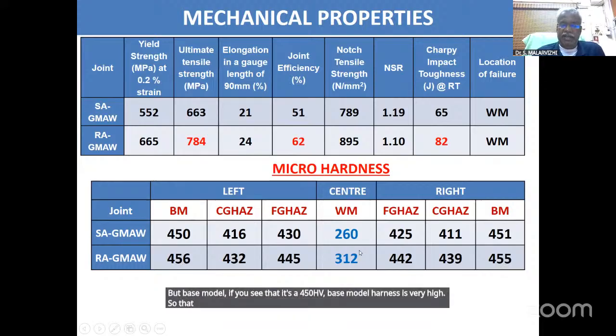So that's why they are going for the austenitic stainless steel filler. And there is a microstructure, in both the processes, the microstructure is composed of delta ferrite in the plain austenitic matrix. There is not much difference in the phase volume fraction of the delta ferrite, only 25 to 27%. But the morphology of the delta ferrite is changed because of the stirring action of the rotating arc, the centrifugal force acting on the weld pool.